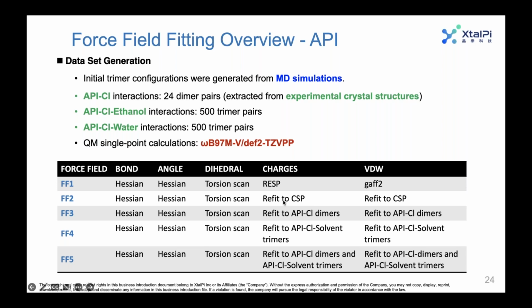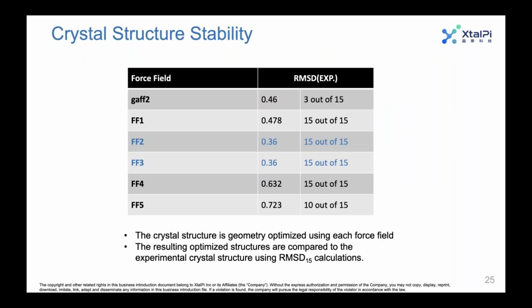So for example, force field 2 was refit to crystal structure prediction of metformin HCl. Force field 3 took the CSP force field and was refit to API chloride dimers, and they get more complex from there. And then we were able to verify the force field performance. So we took the force fields that we parameterized and we optimized metformin HCl crystal structures, and then we compared those structures to the experimental structure. So you can see the out-of-the-box force field is not even able to reproduce the crystal structure, versus the tailor-made force fields, which are all able to reproduce it, except for force field 5, interestingly enough, suggesting it might be overfit. But force fields 1 through 4 all reproduce the structures.